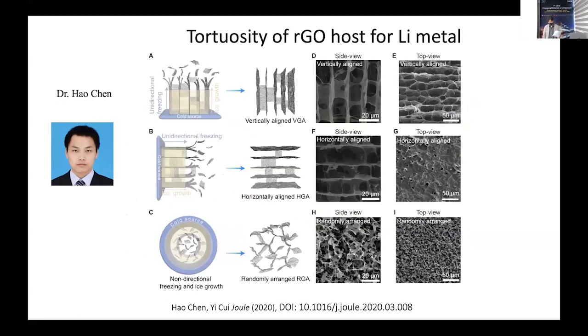So my postdoc Hao Chen recently demonstrated this method: we use a graphene oxide aqueous solution and then freeze it. Once you freeze that, you can align the ice crystals, and the graphene oxide will be aligned. So we can align it vertically, that's on the top row. Middle is horizontal. We can also use a kind of beaker to freeze from the side. Then you align it radially, and you have this random orientation. So this SEM image shows the vertically aligned, horizontally aligned, and randomly arranged graphene oxide. We use that to do lithium plating and stripping.